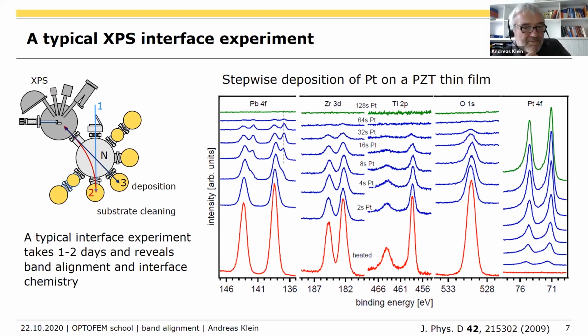You can do oxygen 18 exchange experiments with SIMS. That's a possibility to see what the oxygen vacancy concentrations are. And in some materials, you can also do luminescence measurements, because, again in strontium titanate, oxygen vacancies are giving a luminescent signal. Yeah, very important, but very difficult to really get a hands-on this.